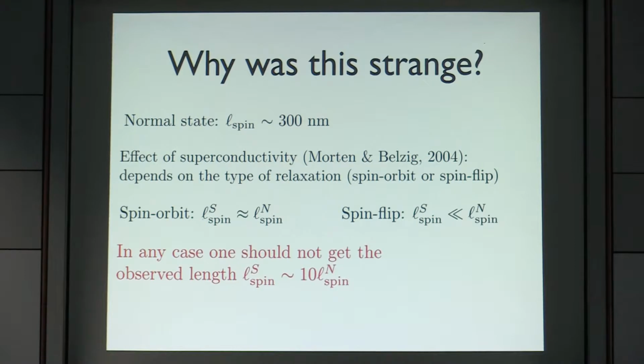Now, why is this strange? Well, you would assume that superconductivity, of course, does something to the spin relaxation. I told you already that the spin relaxation length in the normal state, for example, in that aluminum that was measured, was of the order of 300 nanometers. The effect of superconductivity on the spin relaxation length had been evaluated before. This was work by Morten and Belzig, 2004.